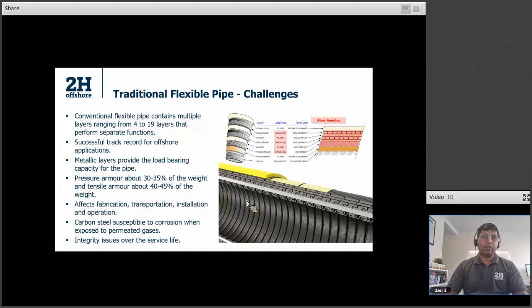These carbon steel pipes are the heaviest components in a traditional flexible pipe. Like the pressure armor, which provides the resistance against hoop stresses, is about 30 to 35% of the weight of the total structure. And similarly, the tensile armor layers, which provide the axial strength, are about 40 to 45% of the weight of the full structure. This additional weight affects and has implications on fabrication, transportation, installation, and operation.